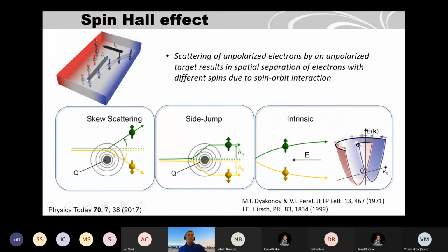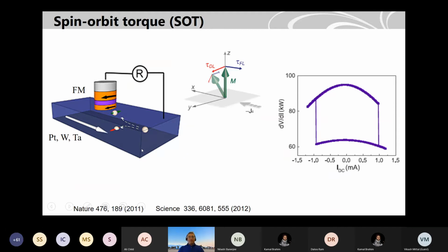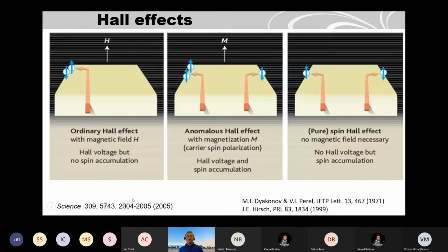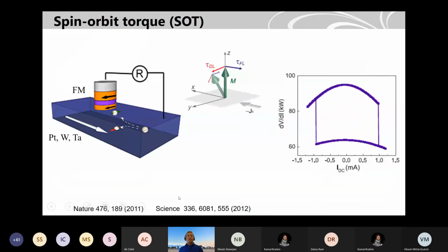So this is again a schematic. When you pass a charge current, your spins are accumulated on both sides of the material, and this gives a spin current in this direction. That is called a pure spin current, because there is no charge current here. Okay. Then people thought, as you see, the spin Hall effect was discovered in 2004 or 2005, and exactly 5-6 years after, people could utilize it to switch a magnet. For example, here you take a metal of tantalum, platinum, or tungsten, which is very heavy.